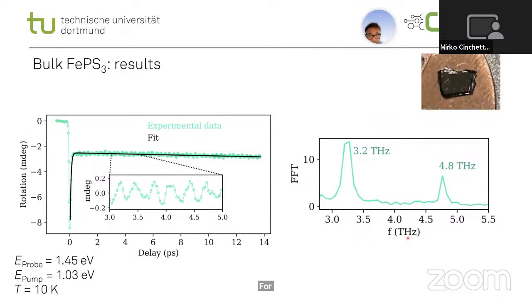We can follow the magnetic field dependence of the frequency of the lowest branch of this phonon-magnon polariton, and this follows what was also reported in the literature from the Raman spectra. So we have this behavior. The point here is that by using the d-d transition and an applied magnetic field, we are able to generate a hybrid phonon-magnon mode at 9 Tesla. So this is the story so far.